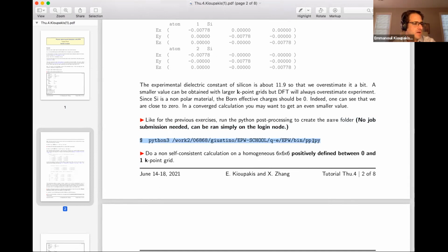A question about which value can have the bandgap value? Good question. So if your bandgap, it should be, either should have it. If you have a fine enough grid, you should be able to find it from both. The trick with silicon is that the conduction band minimum is not on a high symmetry point. It's along the gamma-X direction at a relatively low symmetry point. So you'd have to first do a band structure calculation to find where the gap is. And once you know the value on a fine grid, then you know what kind of spectra to expect. So it's a good question.